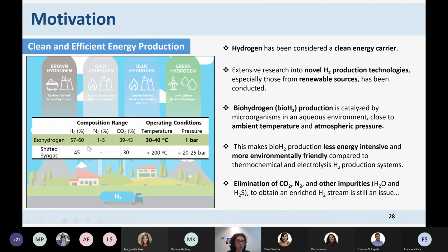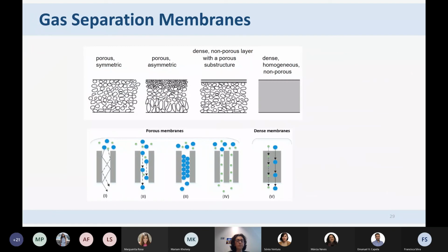So biohydrogen has around 57 to 60% of hydrogen, while shifted syngas has 45. And the conditions are: it is produced at 30 to 40 degrees C, while shifted syngas is more than 200 degrees C, and the pressure is 1 bar, while the pressure for the syngas is between 20 and 25 bars. So this seems to be a very nice application for our membranes, at least to test our membranes and see what comes up. So here is again this duality that I was talking to you about before.